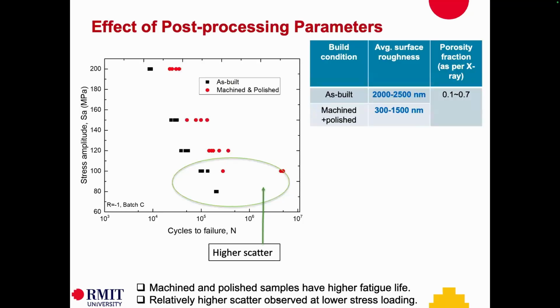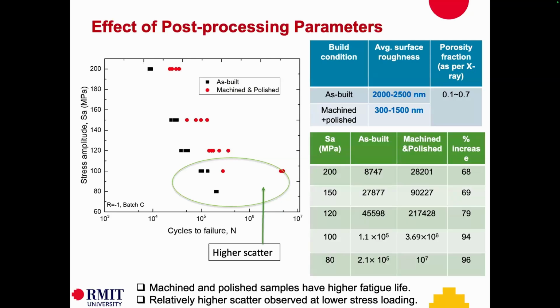Then we looked at what happens if we do post-processing, which is a second step to improve fatigue life. You can see the black dots are as-built data, and the machined and polished data are red dots. Again, for low amplitude loading, we see higher scatter. And for high amplitude loading, we clearly see machined and polished specimens are grouped together, and they improve the fatigue life. You can clearly see the roughness changes. Machined and polished surfaces have a roughness of 300 to 1500 nanometers, but as-built can have 2500.